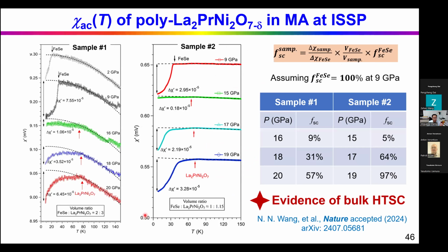So basically, we put the iron selenium and the praseodymium doped sample in the coil and measure the AC susceptibility. You can see at lower pressures, we only observe the transition from the iron selenium, and the transition temperature, about 30 Kelvin, is consistent with our previous study. At about 15 to 16 gigapascal, you see the transition from iron selenium disappear, but we observe some kind of decrease anomaly at high temperatures, and this becomes clearer with increasing pressure. You can see at 20 GPa, it shows a very clear change of this AC susceptibility.